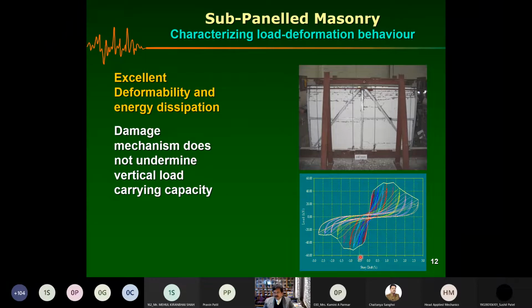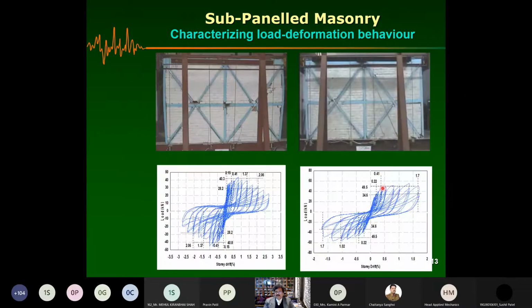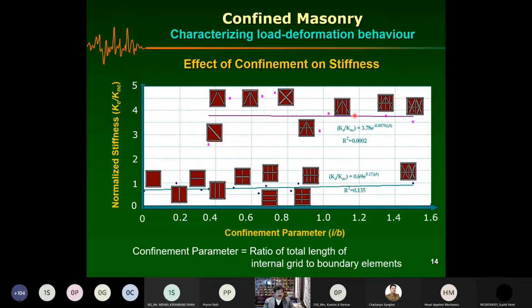Masonry usually cracks at 0.5%, and now you're going up to 2.5% or at least 2%, maintaining significant strength, you see. And you can play with whether these members are continuous or they stop, only horizontal members continue, or you can have the diagonal members continuing. So you can play with this strength and stiffness and still design your wall.